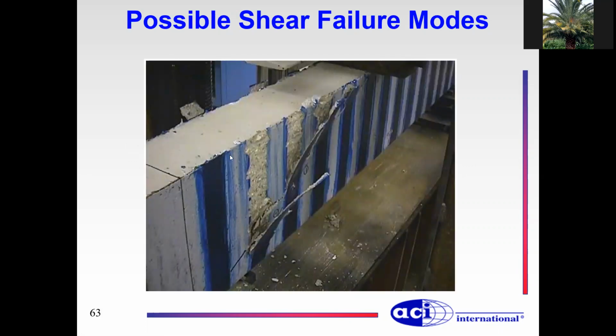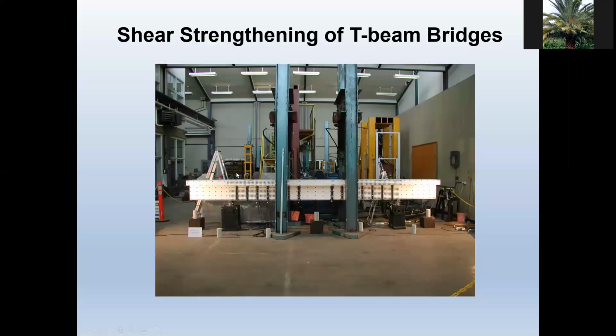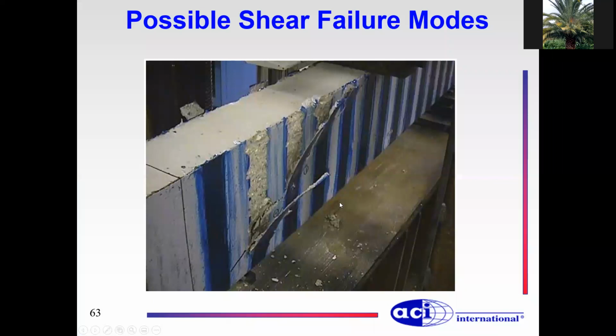So when you put vertical strips, and you load this, the FRP is going to resist. It's going to have tension in it. You see this is in black, until the stress level in the FRP becomes of such magnitude that it delaminates from the concrete. I want you to pay attention here to this delamination surface.